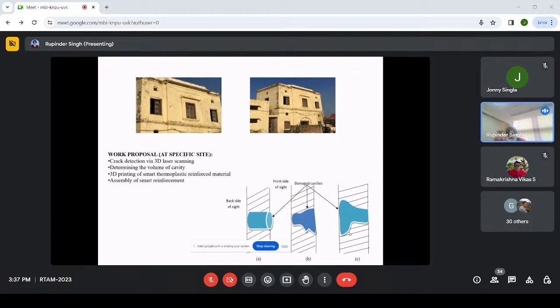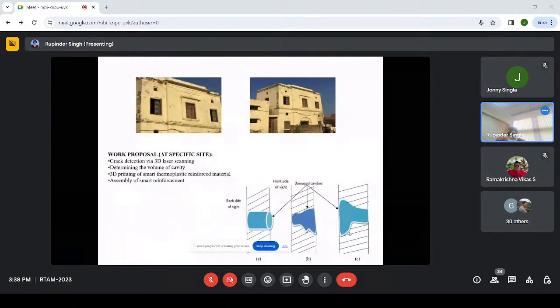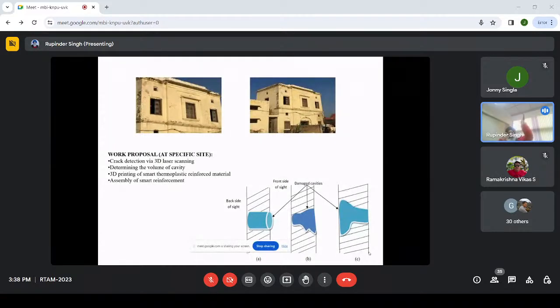Like, there is a company called Hilti, which is a German-based multinational company, which provides an epoxy solution for these types of cracks, right? So what we do is, for the crack propagated, we take an epoxy, we use heat, temperature, and pressure, which basically pushes the material and fills the crack like this. But if the crack is of type 1 and type 2, as shown in figures A and B, this can be easily filled. But in the case of the crack shown in part C, it may not be filled, specifically if the crack is propagating in an upward direction or coming in a downward direction. So keeping all these things in mind, we have to develop a smart solution which can work once it enters into the cavity.